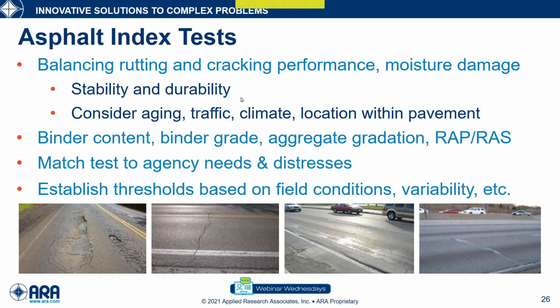For asphalt, generally speaking, performance tests for mixtures try to achieve some kind of balance between rutting and cracking performance. And also there's usually some kind of moisture damage component to that. So you want a mixture that is stable, and you want to make sure that it's durable. In the performance tests, you want to consider aging, traffic, climate, even location within the pavement. Now the dials you can turn in order to meet any of these criteria are the binder content, even the binder grade, the type of aggregate you choose, the gradation of aggregate you choose, and how much recycled asphalt pavement or shingles you will have in the pavement.